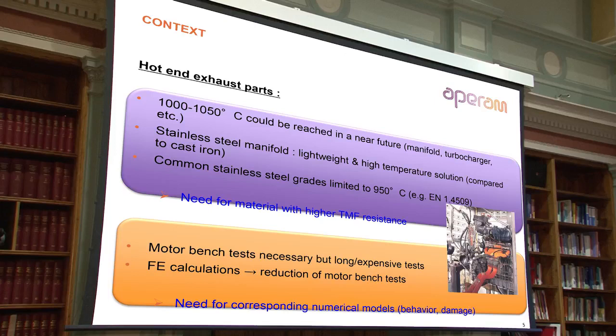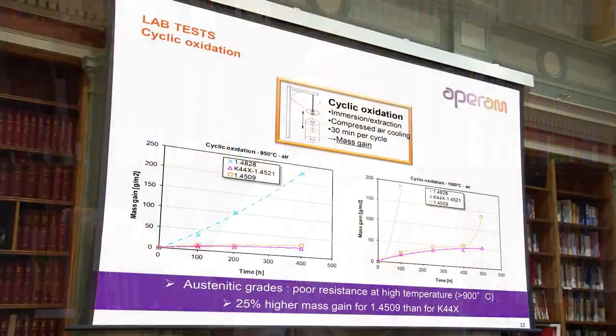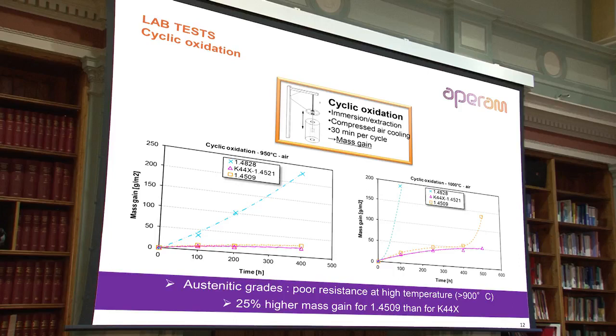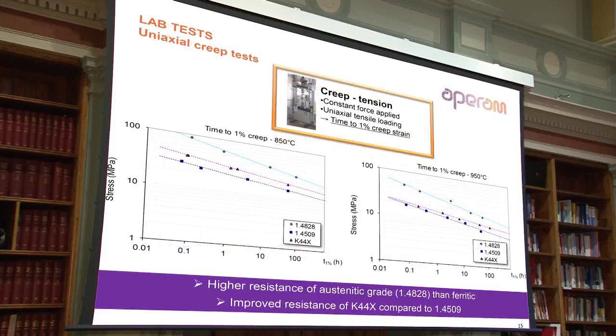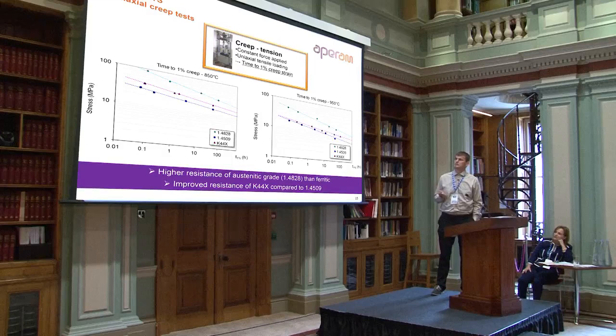The existing optimum material, which already contains niobium and titanium, grade EN 1.4509, can only withstand temperatures up to 950 degrees centigrade. By increasing the chromium level from 17 to 19% and adding 2% molybdenum, the niobium alloyed variant can meet the increased service demands. Enhanced tensile, fatigue, cyclic oxidation and creep properties are all achieved. Mechanistically, the nature and distribution of the niobium-rich carbides is changed, providing a cost-effective solution in which the niobium still provides stabilization against high-temperature sensitivity to localized chromium and weld decay.